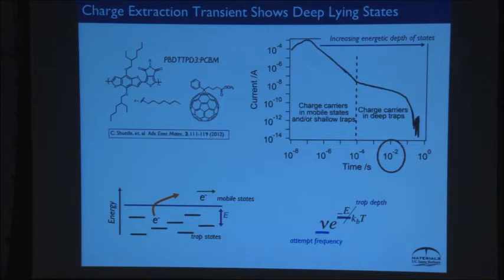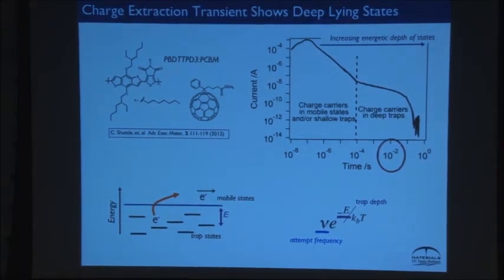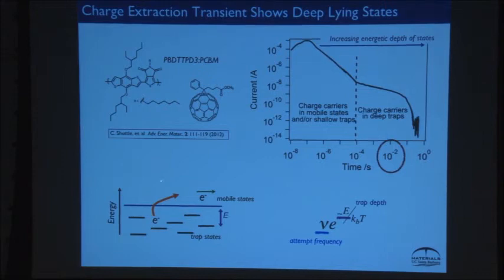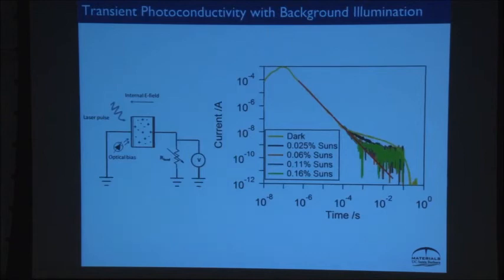And the simple explanation for this is they're trapped, right? And there are a variety of models one can look at to understand this. But one model is you just say there's some extended states, and you can hop out of a trap, and then you make your way out. And when you do that, and you put in an attempt frequency for jumping out, you get a number of about 0.4 eV or so, which is kind of plausible with these tails that we see in the optical spectrum.